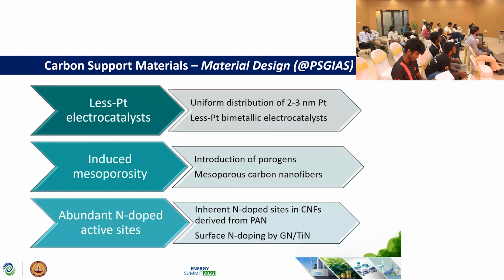So our strategy to design the carbon-based support materials at PSGIAS is to develop materials with less platinum electrocatalyst, which means we try to produce a uniform distribution of approximately 2 to 3 nanometer platinum particles throughout these support materials. We are also involved in producing less-platinum bimetallic electrocatalysts. In that way, we try to increase the effective utilization of platinum electrocatalyst and reduce the platinum loading. Secondly, we focus on the intentional introduction of mesoporosity into carbon support materials. This we do using electrospinning, and I will explain how we are doing it in the forthcoming slides.